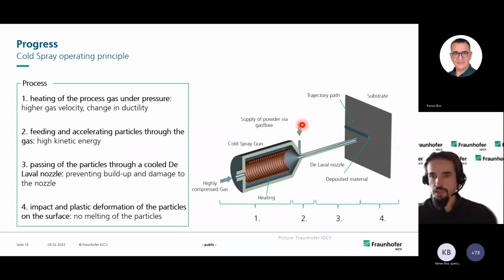The powder is then fed into the nozzle here, and then afterwards the powder and the gas stream is guided through the nozzle to the Laval nozzle, and the powder is thereby accelerated to supersonic speeds, and then impacts a substrate, and by impacting the substrate, the particles deform plastically, and afterwards, with the subsequently impinging particles, all the particles form a dense layer, and the bonding mechanisms behind that are a combination of a mechanical interlock and a metallic bonding.